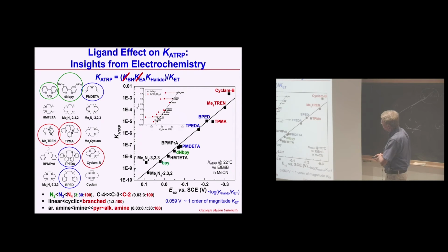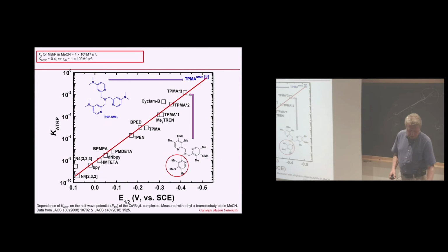So these champions, circled in red, practically take all of these structural features already. So how can we go further? In fact, one possibility is to put electron-donating substituents. You could see here what happens if I put this pyridine containing dimethyl methoxy substituents, and now if I put one of these groups, it becomes 10 times more active, 200 times, 1,000 times. If I go to dimethylamino group, it becomes 10,000 times more active. So this is the way you can go to more active systems.